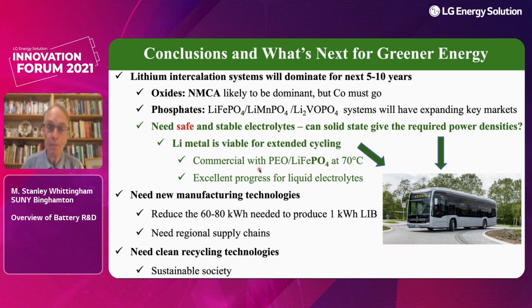It's commercial using a lithium metal, PEO electrolyte, and lithium iron phosphate at 70 degrees centigrade. This is Blue Solutions in France. It's used with cars, which are shared cars, so they run as a fleet, so professionals are looking after them.